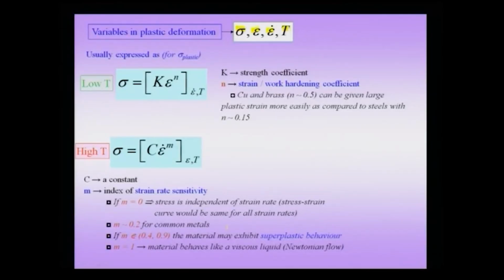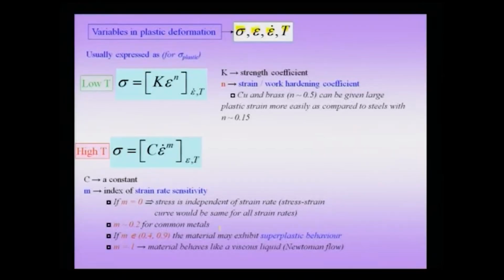Normally, the effect of strain rate comes into play only when you increase the strain rate by a few orders of magnitude. Suppose I am conducting a test at a strain rate of 5 per second and double the strain rate to 10 per second, this is not expected to affect many of the properties, including ductility or the ultimate tensile strength. But suppose I increase the strain rate by a few orders of magnitude, from 10 to say 10 power 4, then I do expect that the overall behavior of the material is going to change.